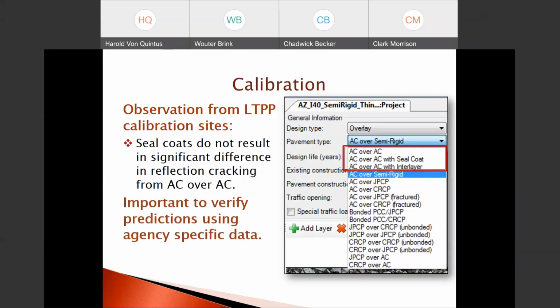Thus, it is important to verify, because that is not the case with some agencies, where they have found and verified that there is a contribution, especially from using some of the interlayers as well as seal coats, in delaying, not preventing, but delaying reflection cracks. And it's important to verify the predictions using agency-specific data.